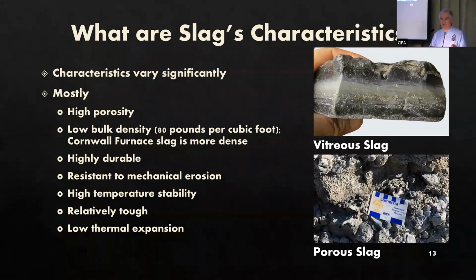Now at Cornwall Furnace, the slag that it produced is about 160 pounds per cubic foot. Again, it reflects the differences in the composition and how the furnace is operated. In addition, other characteristics of slag: the slag tends to be highly durable. It's resistant to mechanical erosion. It can withstand high temperatures. It's relatively tough compared to other rocks, and it has a low thermal expansion.